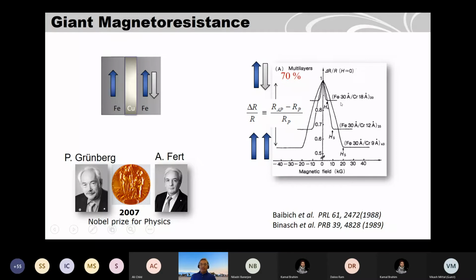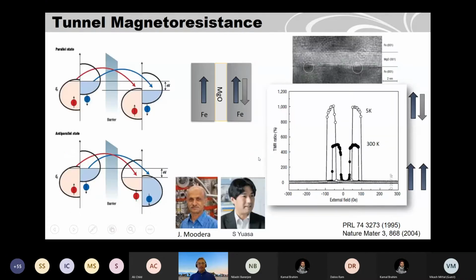So to increase the sensitivity of the devices, the change in the resistance they saw was around 70%, which was very large compared to anisotropic magnetoresistance, which was around 1%. This gives rise to the name giant magnetoresistance. And this has been used in magnetic hard disks. Then after several years, people actually used tunnel magnetoresistance. In between these two ferromagnets, they put an insulator, magnesium oxide. It's a normal insulator, so electrons have to tunnel through.